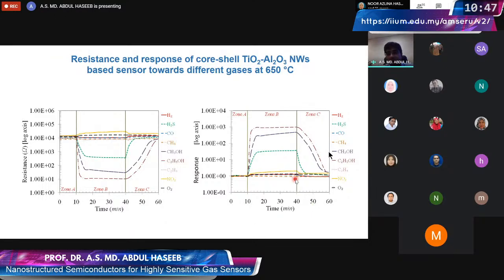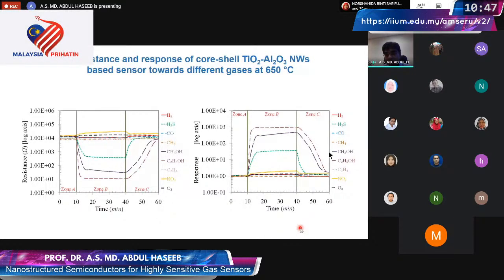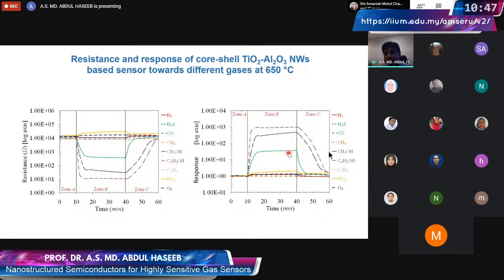And as we see, the response of the sensor, the TiO2 aluminum oxide mixture, depends on the gas. For some gases, the response is very low. And the response is quite substantial only for 3 gases here. So one is hydrogen sulfide, another one is methyl alcohol, another one is ethyl alcohol. So these are the 3 gases which respond very well towards these gas sensors.